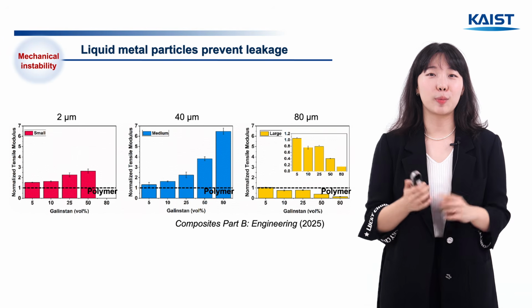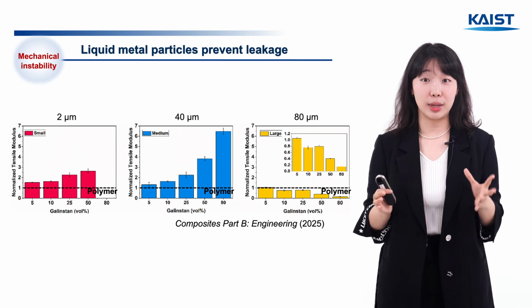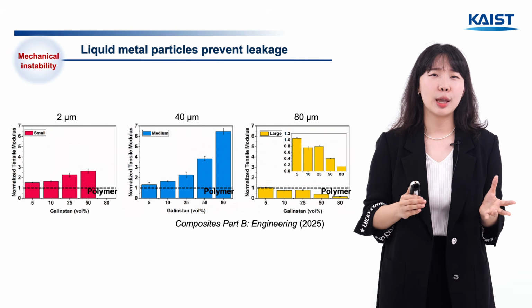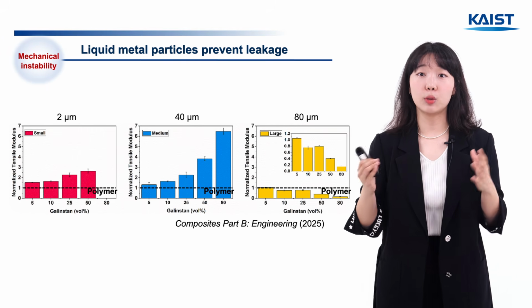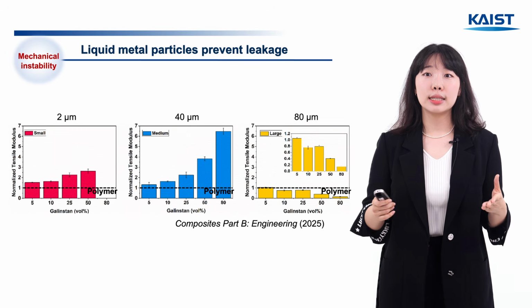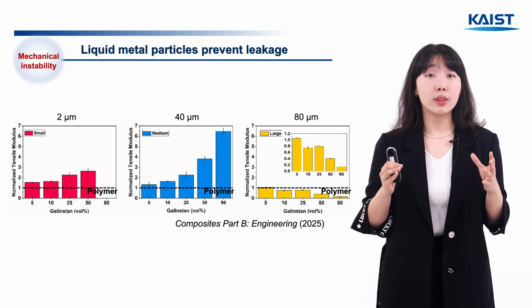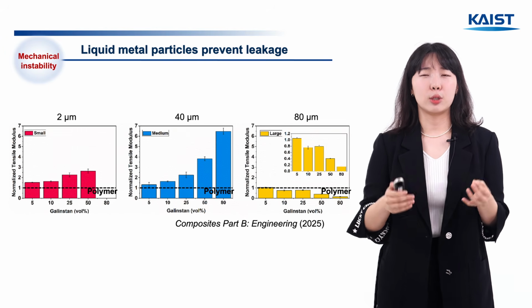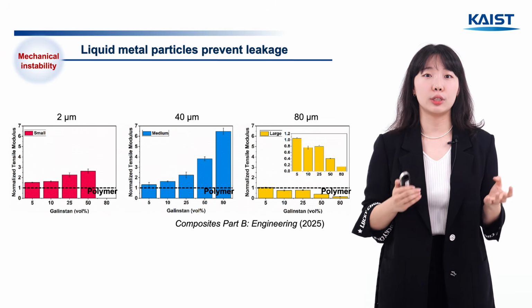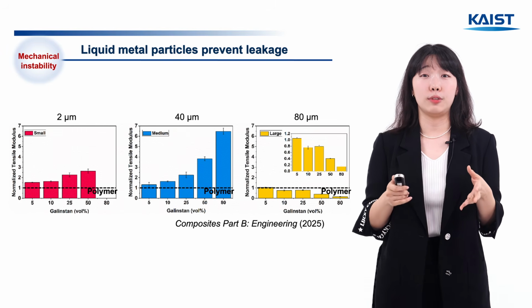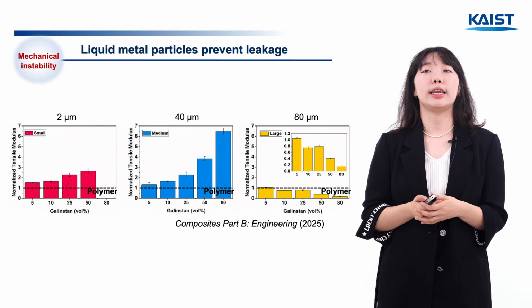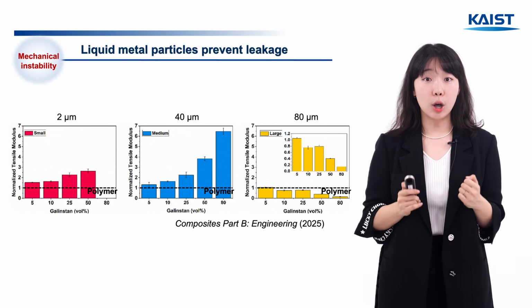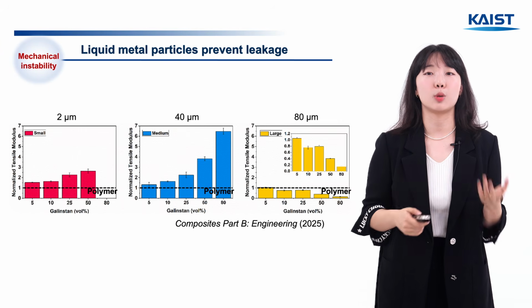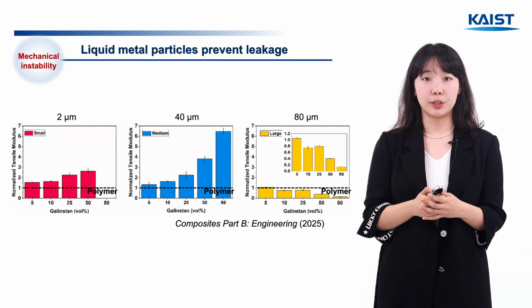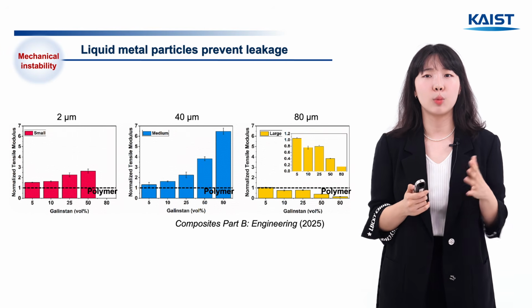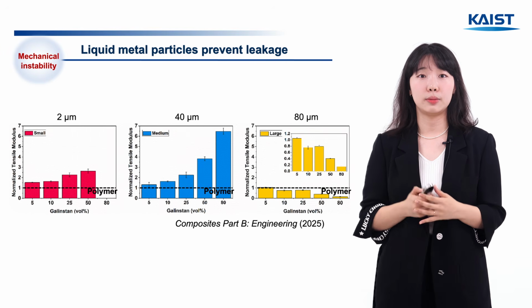So, when liquid metal particles are mixed with an elastic polymer, such as PDMS, you might expect that the composite will get softer as you add more of them, since they are all liquid. And with large particles, that's what you would think. The more you add, the lower the modulus drops, even below that of the polymer alone. So eventually, it's softer than just the polymer. But small particles behave the opposite way. Because of the high Laplace pressure, they resist compression, so as you add more, the modulus actually goes up.